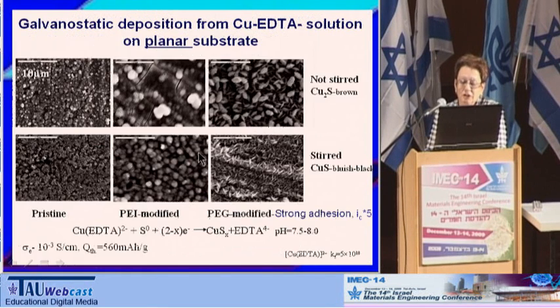The second electrode material, which we started to develop in order to eliminate the sloping character of the curves, is copper sulfide. We used also electrodeposition to prepare thin copper sulfide films. We have found that increase of the deposition time and also current density is followed by peeling of the films from the substrate. However, simple modification of the electrolyte used for the deposition of this material by polyethylene imine or polyethylene glycol dimethyl ether additives not only changed the morphology of the deposits, but also enabled preparation of thick cathode films at the deposition rate 5 times that found for the pristine cathode.